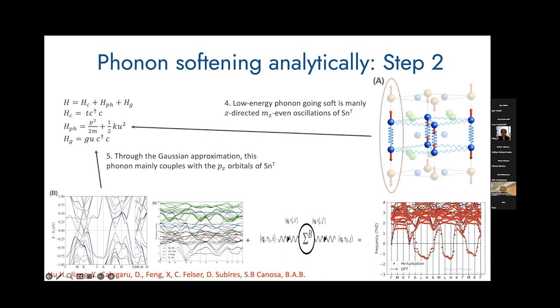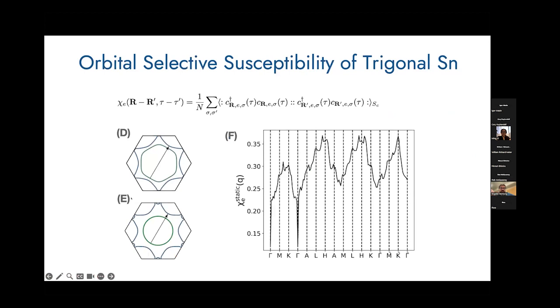Now, this fit has several properties. For example, now you can see that the H point is the lowest. And this property, you can understand it immediately from just the susceptibility of the trigonal tin. As I mentioned, there's nothing to do in the susceptibility of the entire system. It's got no features. But if you do the orbital, looking at the electron phonon coupling of the tin with the tin orbitals, you're going to find that the tin susceptibility can be separated into two contributions: an on-site contribution that lowers the phonon energy, omega squared, below 0, and then a nearest neighbor contribution that's basically the hopping on a triangular lattice, made by triangular tin, which gives the dispersion of the phonon.